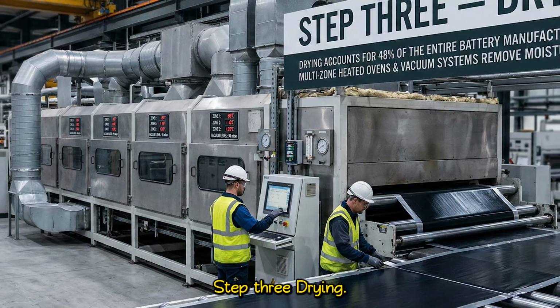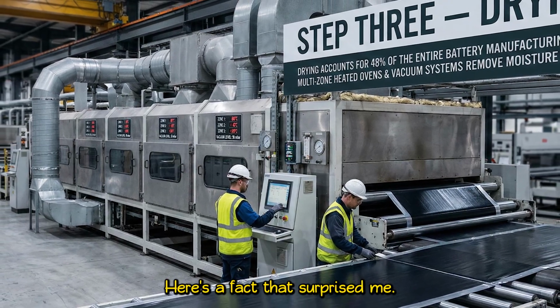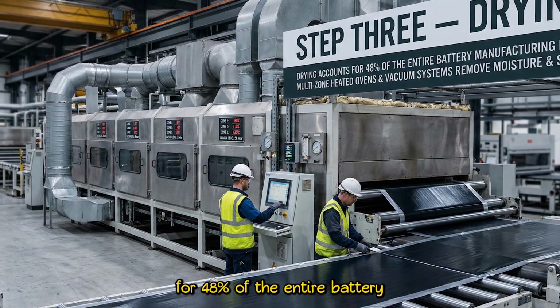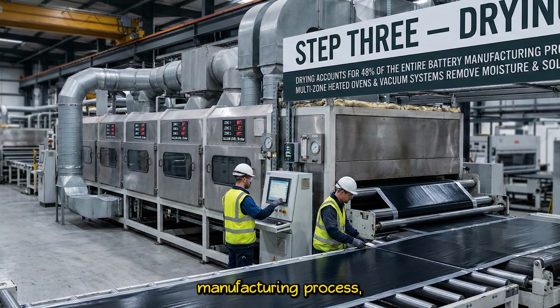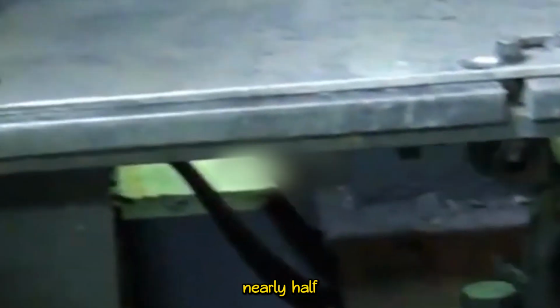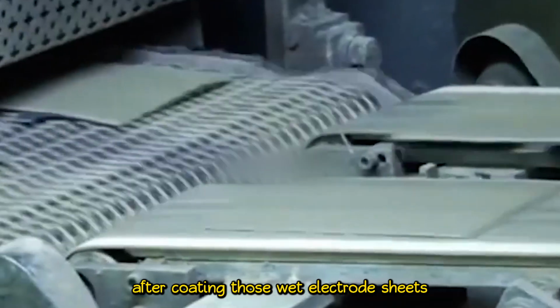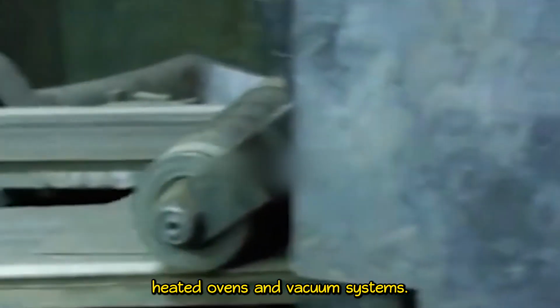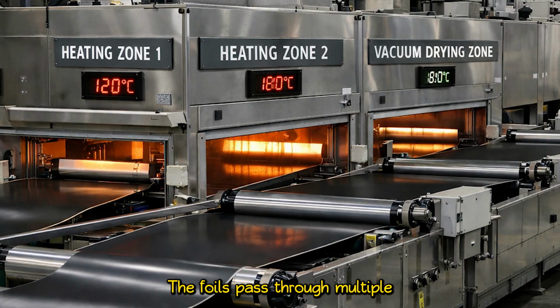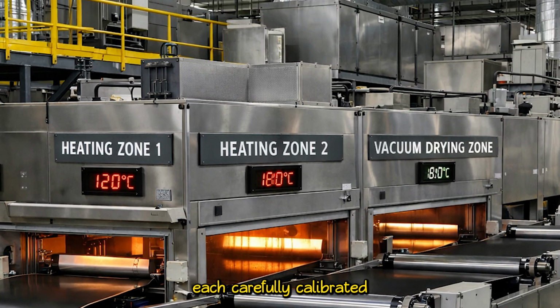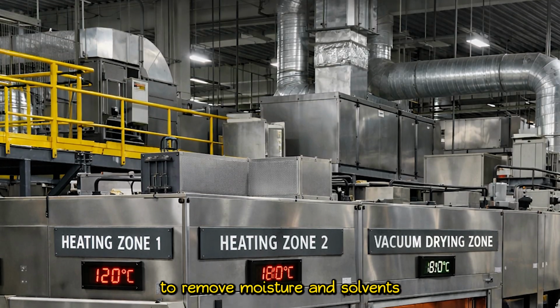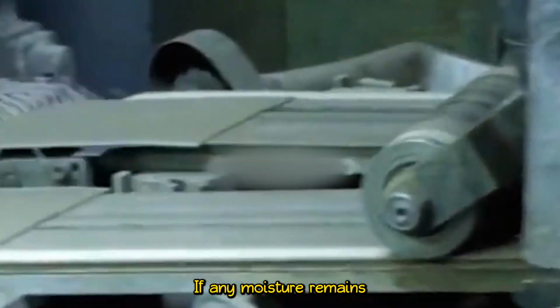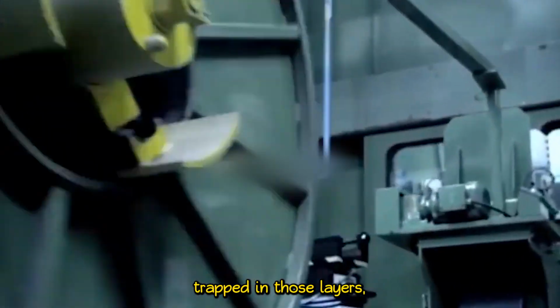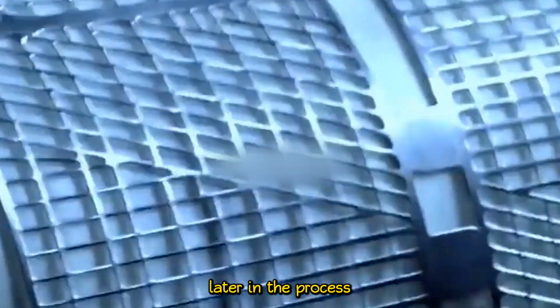Step 3. Drying. Here's a fact that surprised me. Drying accounts for 48% of the entire battery manufacturing process. Nearly half. After coating, those wet electrode sheets need to be dried thoroughly using massive heated ovens and vacuum systems. The foils pass through multiple different temperature zones, each carefully calibrated to remove moisture and solvents without warping the material. If any moisture remains trapped in those layers, it will react with the lithium later in the process and destroy the cell from the inside out.